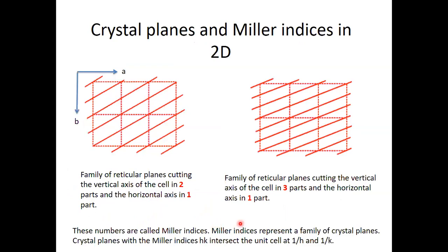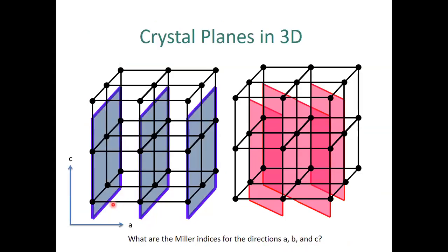So what number do H, K, and L have to become so that 1 over that number will be infinite? Well, basically, the Miller indices would need to approach 0. We can say that they are 0. Of course, strictly spoken, we cannot divide by 0, but we can divide by extremely close to 0. Okay, so overall, therefore, the Miller indices here would be 1, 0, 0.